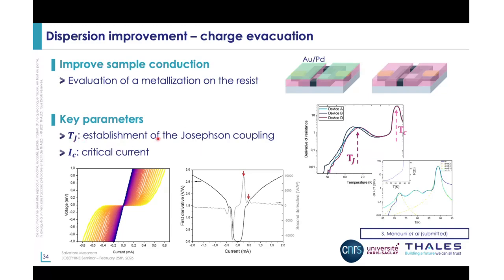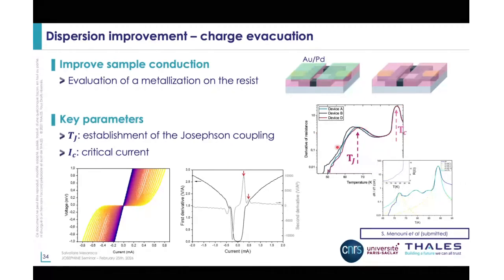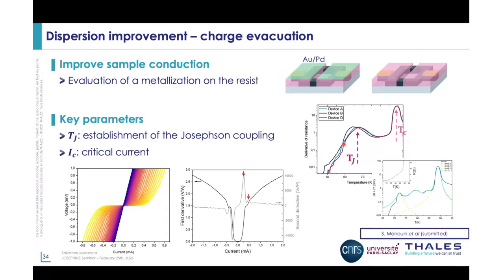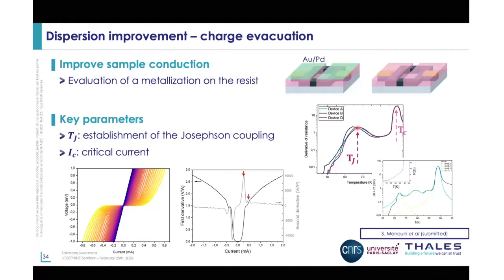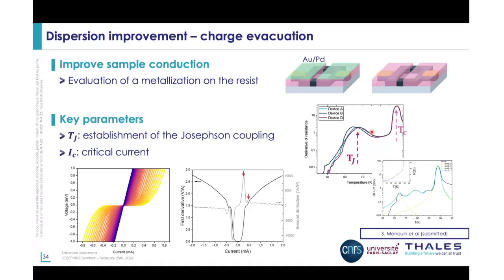So the TJ, which is the establishment of the Josephson coupling temperature, because whenever we do the RT measurements of those devices, we have the first transition temperature. Here you see in the derivative, you have the first transition, which is the transition of the electrodes. And then you have the transition where actually the coupling is onset across the barrier. And if you are lucky enough in a good sample, you can see that we have one TJ only. That means that the 8 junctions creating the device were actually pretty well uniform, and they were all having an onset of